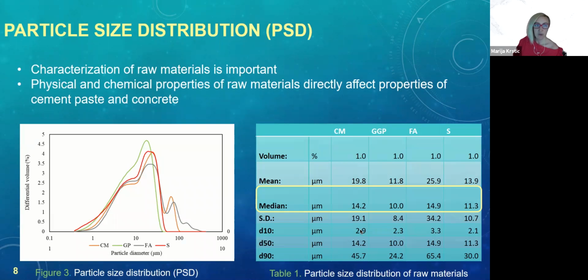We have performed some characterizations of this material because physical and chemical properties of raw materials directly affect properties of cement paste and concrete. By using a laser particle size analyzer, we obtained the particle size distribution of cement, fly ash, slag, and GGP that is used in this study, and we found that the median particle size of GGP was only 10 microns, which was the smallest among all of them.